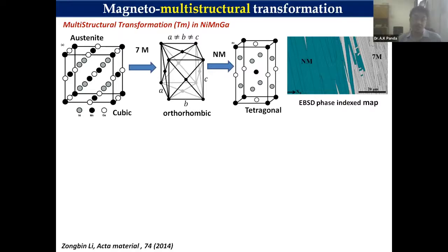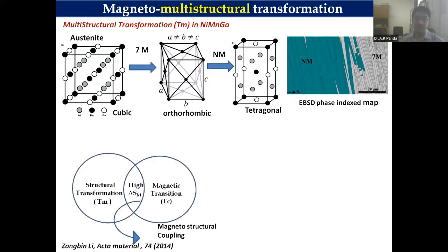and lastly a non-modulated structure. Basically, when we talk about modulations, it is nothing but structural repetitions. Under certain compositions, you do not have the modulations, so it is more of a non-modulated structure. Within the same martensite, you can even find both a non-modulated and a modulated structure. This is typically an indexed electron backscatter map that you see in the top right.